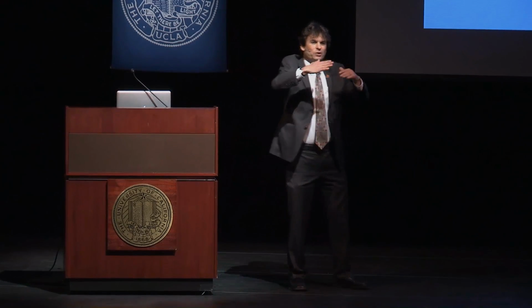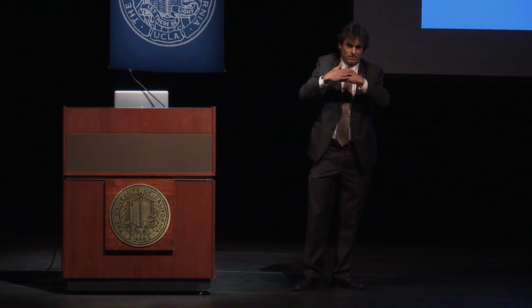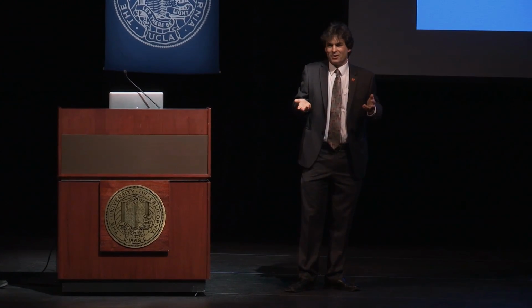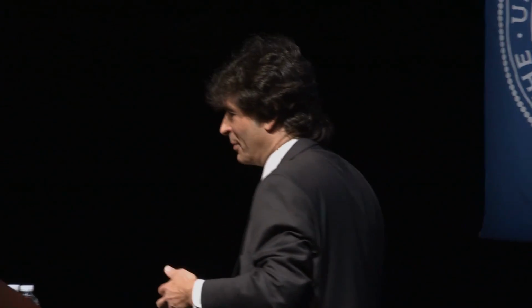In fact, I can tell you that the surface area of graphene is 2,630 meters squared per gram. And when we do this experiment, we've measured above 1,500 meters squared per gram, which means we've measured beyond what you'd get if you put two sheets together, because that would reduce it by half. So we really have individual sheets separated by these pillars. And so we really have what I like to think of as holey graphite. That's why we can make such good charge storage devices. However, capturing CO2 is not one of the things that these are good for. There are many other ways to do that that other people are working on, but it's a good thought. These materials just aren't meant for that.